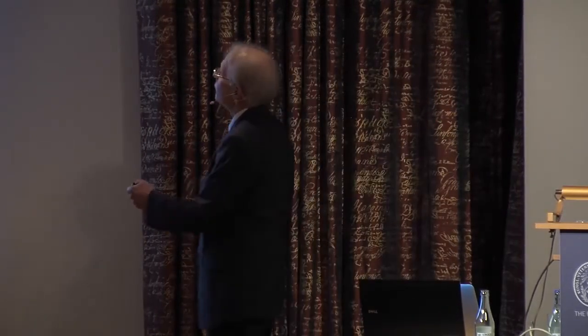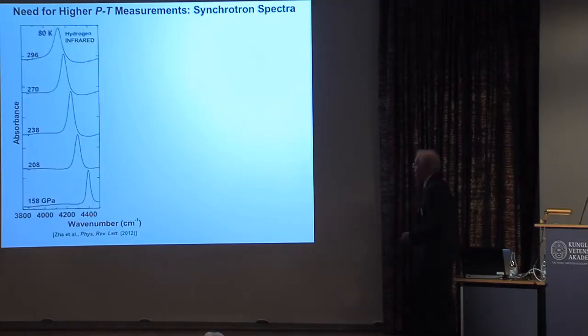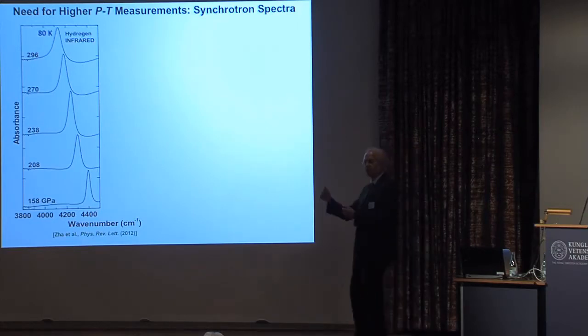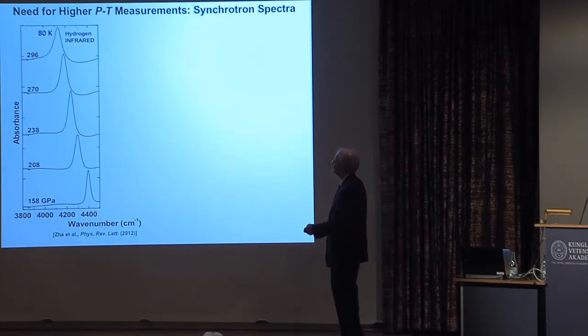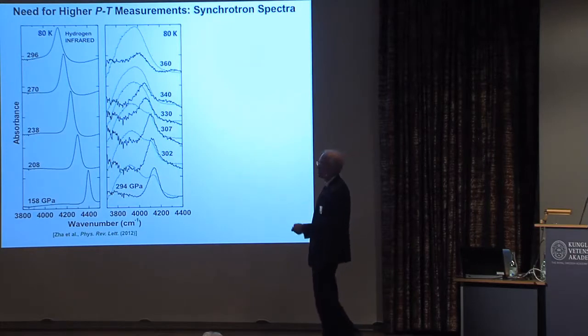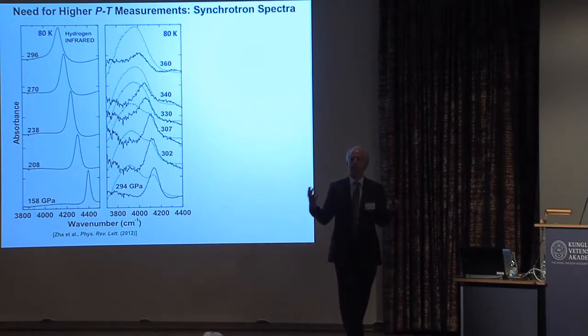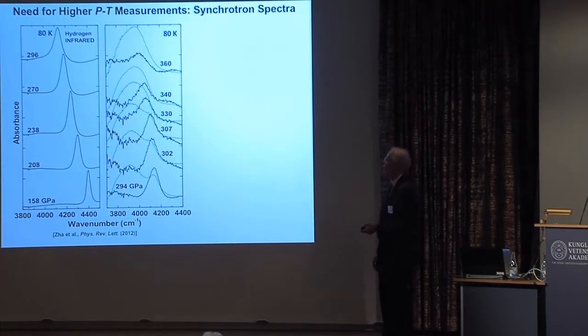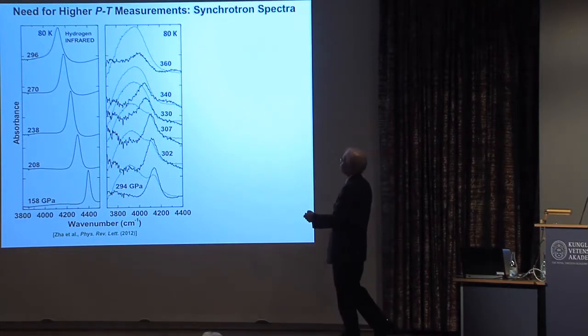We've gone back to this in the last few years, and we've used synchrotron IR spectroscopy principally to probe this to higher pressure. Here we have infrared measurements showing this excitation, this vibron excitation, now up to 360 gigapascals. This, by the way, is well over an order of magnitude higher than the predicted transition pressure by Wigner and Huntington, so the molecules are stable.